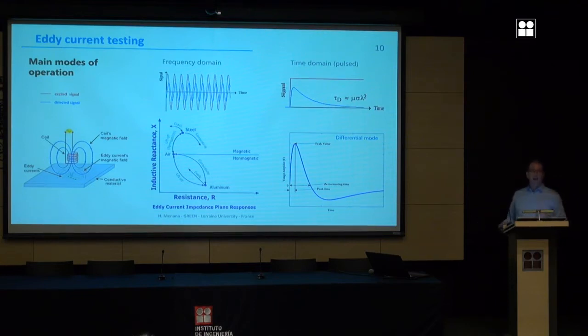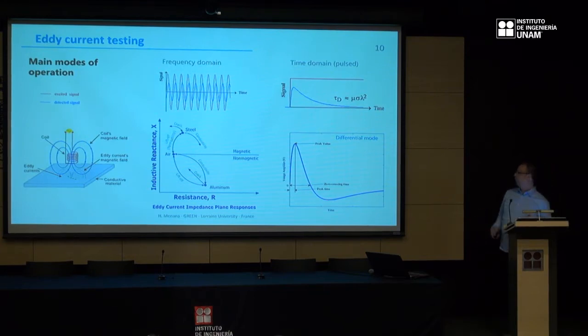So the coil will be fed by a transient voltage or current, and then we use the response, the current variation in the coil. We generally use the current variations: the current when the coil is above the tested material, minus the current of the coil in the air. So we use the variation delta V. For the characterization in this case, we use the peak value, its time of occurrence, the zero crossing time, or this second peak here. These are used to characterize the properties of the tested material, or even the presence of a flaw.